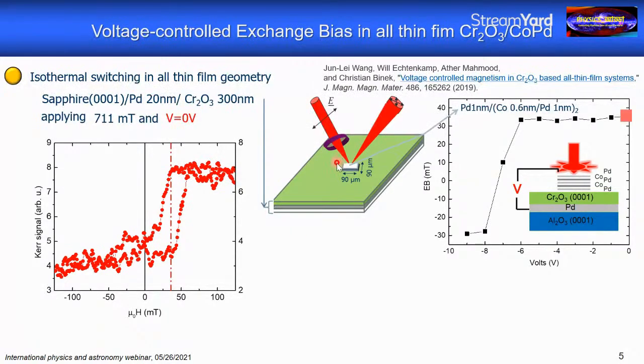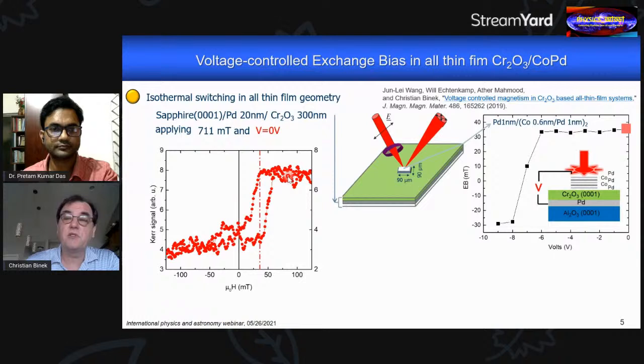And then we deposited a small electrode of ferromagnetic material, again cobalt palladium on top, and it's not that small, so we could still use magneto-optics, polar Kerr effect, to read out the magnetic hysteresis of this ferromagnet. And as you see, if we do that with voltages between 0 and let's say -6 volt, when the system was prepared in a state of positive exchange bias, we kept positive exchange bias.